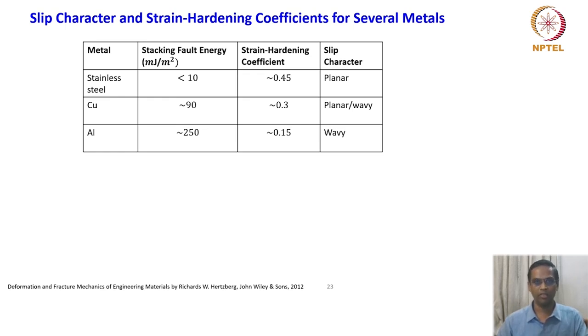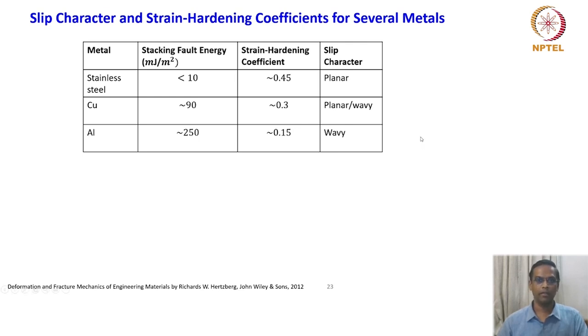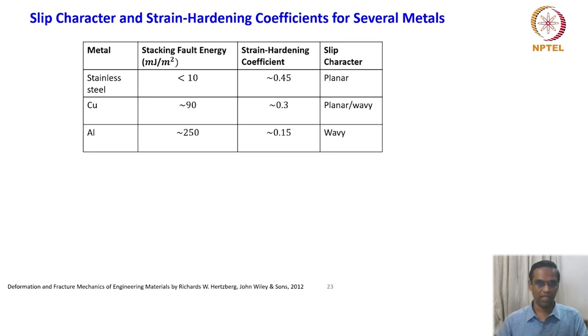Wavy form means it is not in an organized form. On the other hand, for low stacking fault energy materials the same dislocation substructures will appear in a planar fashion — there will be no random waviness, only planar segments. By just looking at the dislocation substructures you will be able to characterize the deformation behavior at a first glance, and then depending upon the interest, you can go to any level of analysis and investigation. The strain hardening coefficients obtained from a simple tensile test tell quite a bit about deformation characteristics if you connect them with the stacking fault energy.